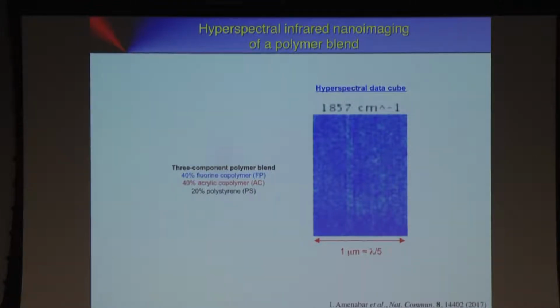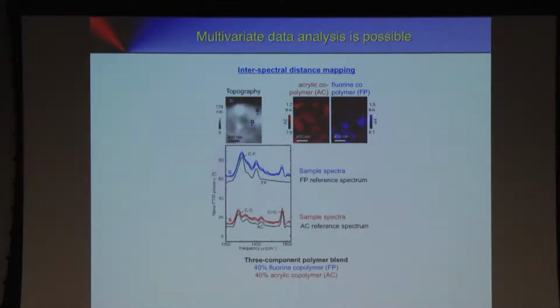And so we were wondering whether our data are good enough to apply standard multivariate data analysis. So we applied that, and we used here a technique that is called interspectral distance mapping. So we take a reference spectrum on the 3 different materials that are composing the sample here. And then at each pixel, we compare the reference spectrum with the actual spectrum at the pixel here. So the reference spectra of this fluorinated polymer and the acrylic copolymer are the black ones.